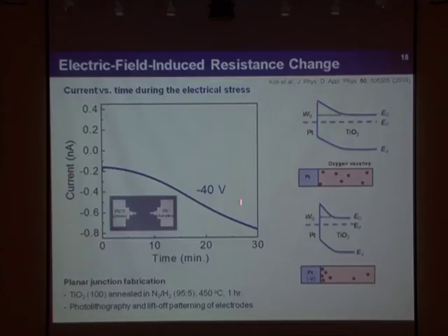It looks like this kind of change can be explained based on the oxygen migration picture. We put the negative bias to the platinum electrodes, and oxygen vacancies can be accumulated at the interface. However, when I apply the positive bias voltage, I also observe a decrease of resistance. So we need some more mechanism—the oxygen migration picture alone cannot explain these two results.